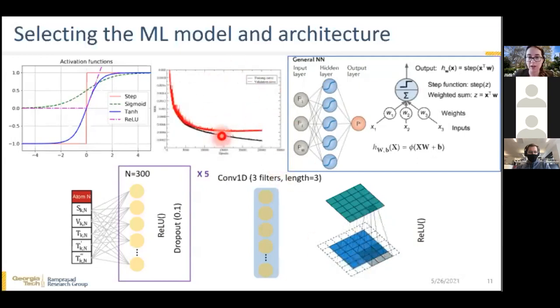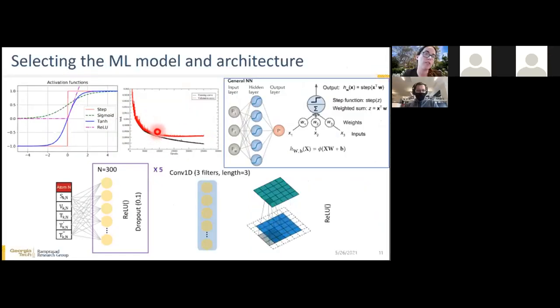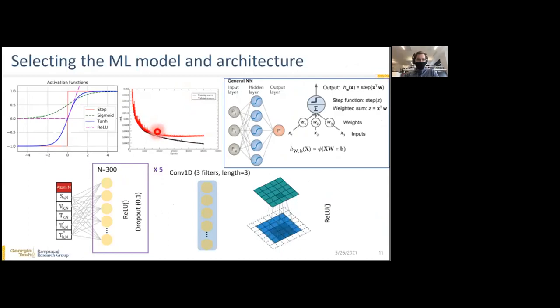This is our learning curves, and we use the mean square error as the error function, and we can see how the validation loss decays with the training until at some point at which it stops improving. So at the point where it stops decaying, that's where we used this early stopping technique and just took the weights at that point.